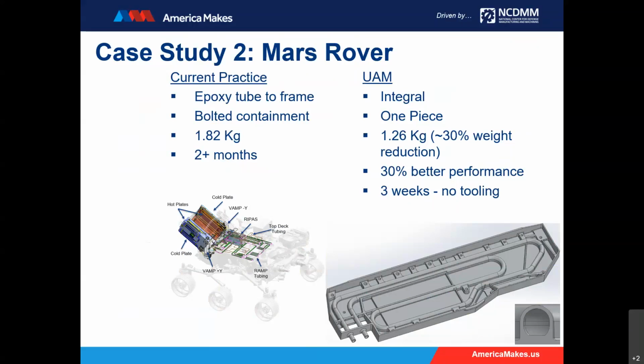JPL was working with us on some other projects, and they asked us to take a look at this. In the process of about a month, we were able to just take their base design and turn it into a 3D printed structure. We didn't try to optimize anything. We just took their pipes and kind of turned that into a 3D printed part. But by making it monolithic, we were able to take 30% of the weight out. We got rid of all the epoxy, all the saddles, without any real redesign. And by getting rid of those thermal breaks, we were able to get significantly better performance.